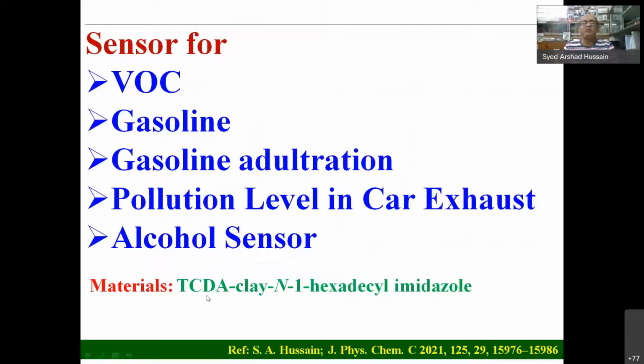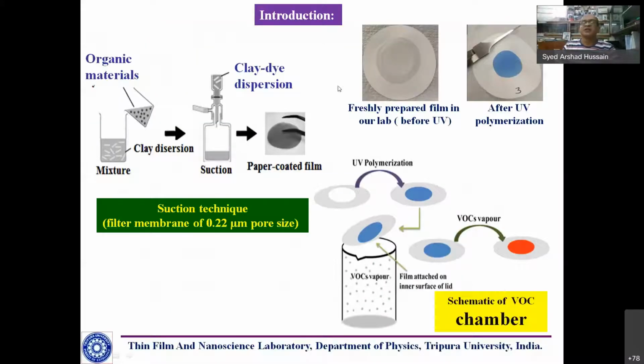So for this, what we did, we made a self-standing film of polydiacetylene clay, and then we also tried with PDA clay and another organic material. This is one system. Then PDA clay and another organic material, synthesized by our collaborator. This is imidazole. So it's two systems. One is clay and PDA. Another is clay, PDA, and imidazole. Okay, so this is how we prepared again the self-standing film on a filter membrane. And after UV, you can see the color. This is the blue phase. So we prepared both the PDA clay film and the PDA clay imidazole film on the membrane, and then we exposed them to UV, converting them into the blue phase.